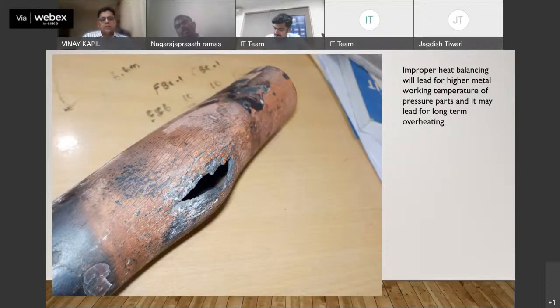This type of superheater tube overheating failure was faced in the superheater zone. Earlier the LT superheater outlet material was T11, and we calculated that the metal working temperature crosses 510 or 520 degrees Celsius. We changed only the superheater outlet tubes to T22, and it was changed one year back, after which we didn't face any problems. But unfortunately, the earlier material also ran for 6 or 7 years of operation, so we are waiting to see what the result will be after 6 or 7 years of operation.